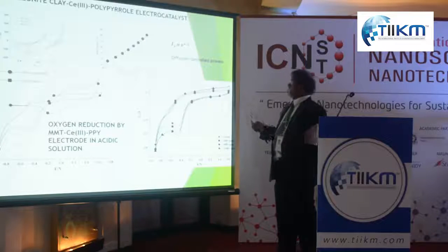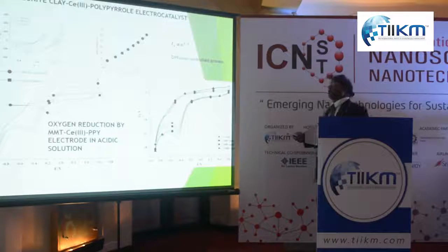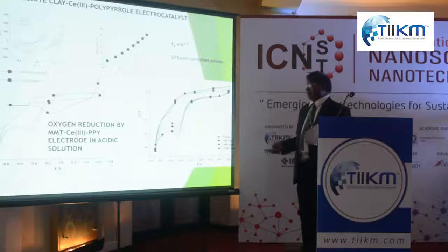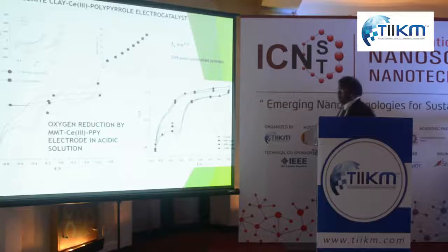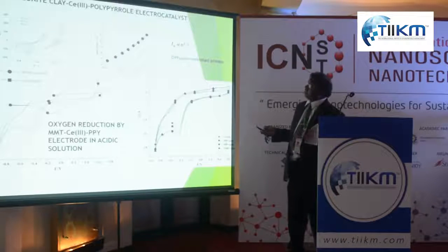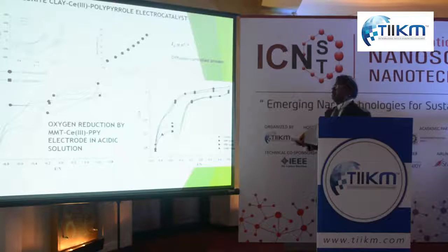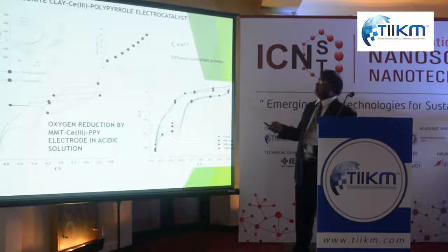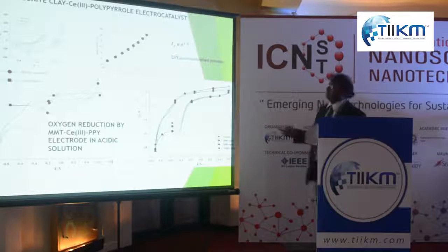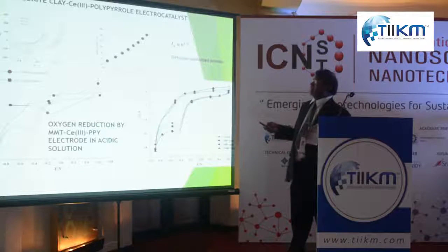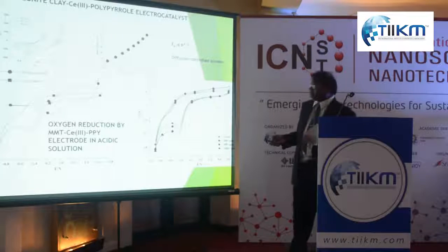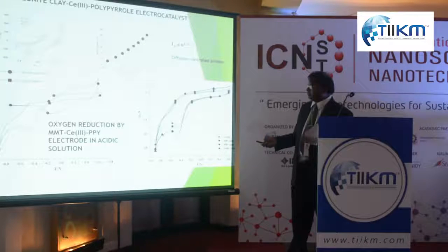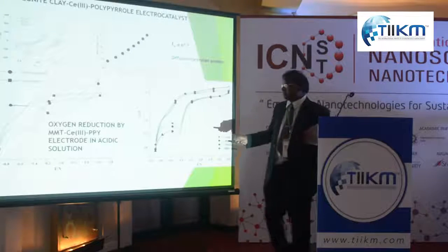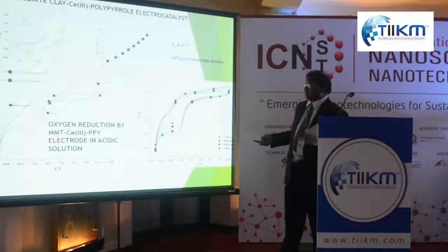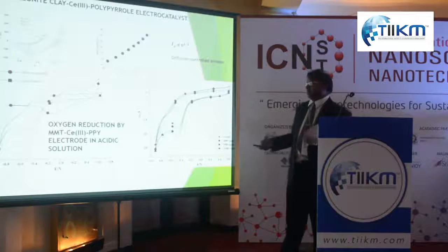So, as you know, cyclic voltammetry is the usual method used to find out the oxidation-reduction behavior of materials. This is an example, cerium polypyrrole. Cerium 4 is reduced to cerium 3, and pyrrole is oxidized to polypyrrole, oxidative polymerization. And the clay is montmorillonite, giving a cerium 3 polypyrrole electrocatalyst. When you have a completely nitrogen-purged atmosphere and scan backwards with respect to the saturated calomel electrode, you don't get any reduction. You see nothing there, no current.